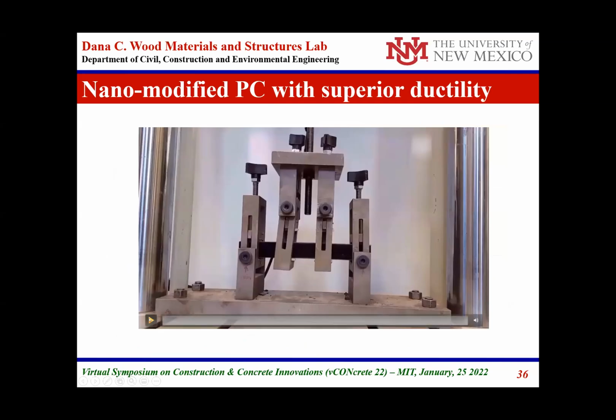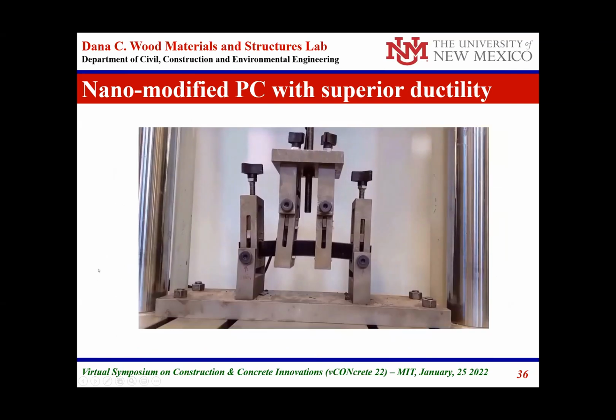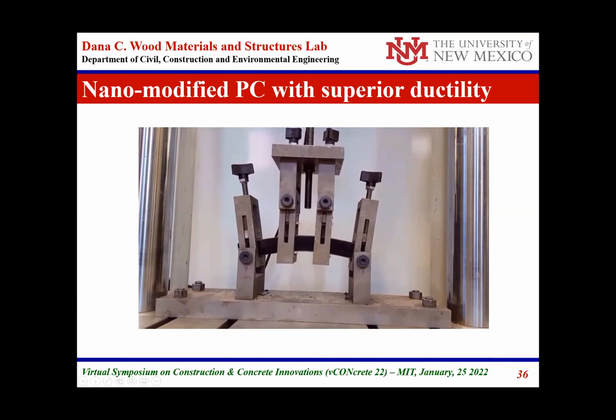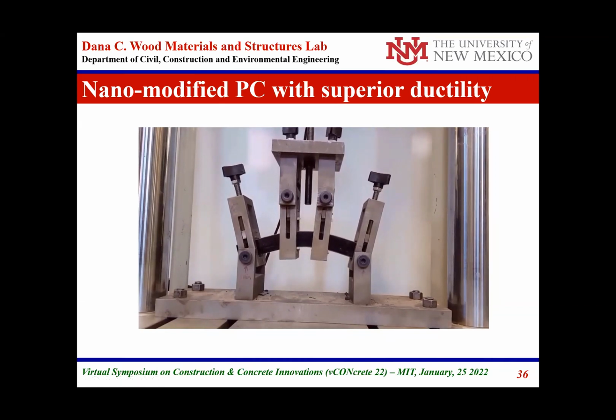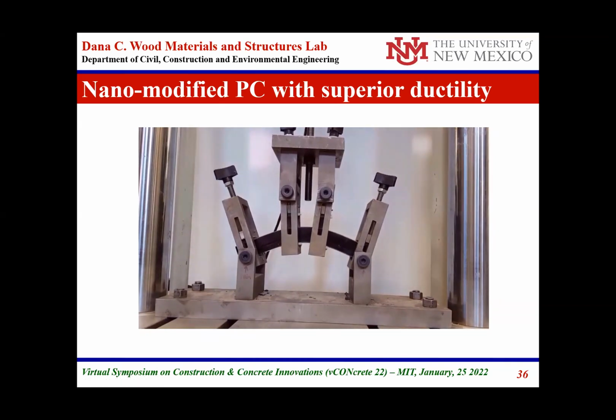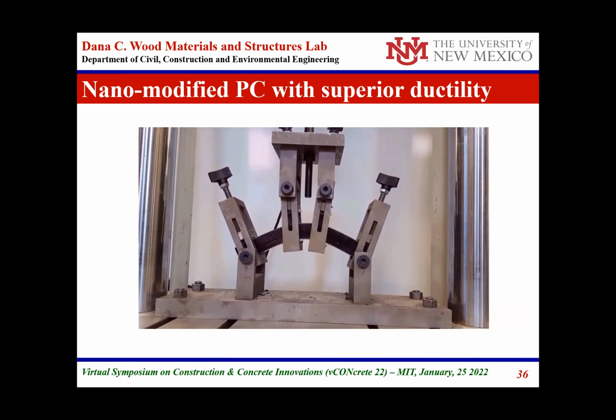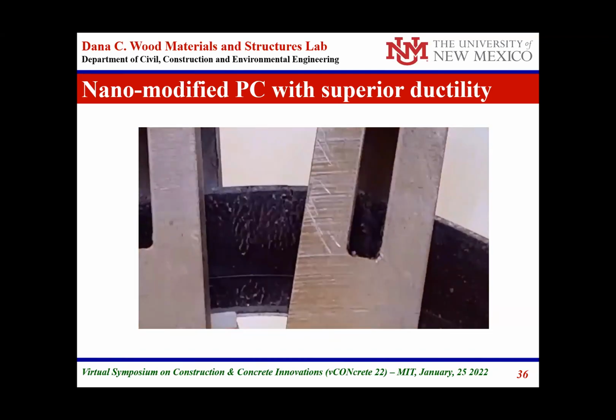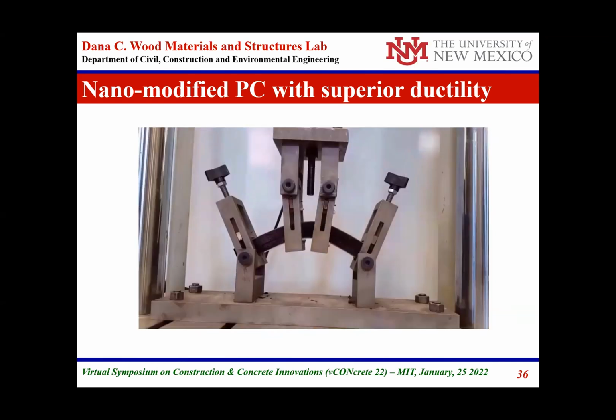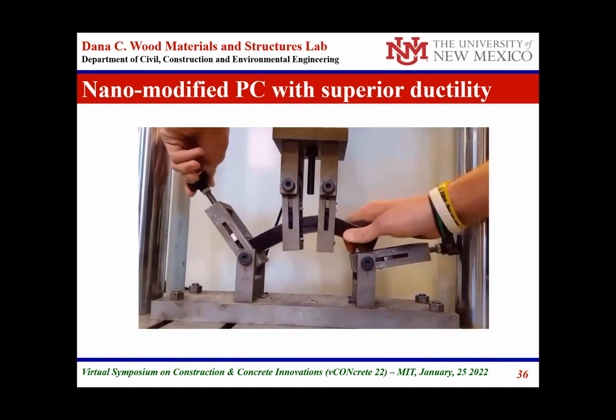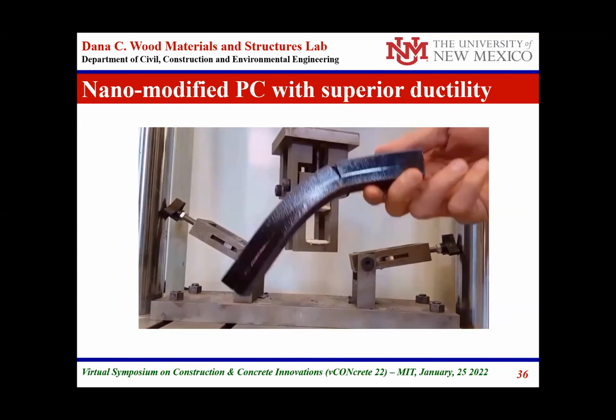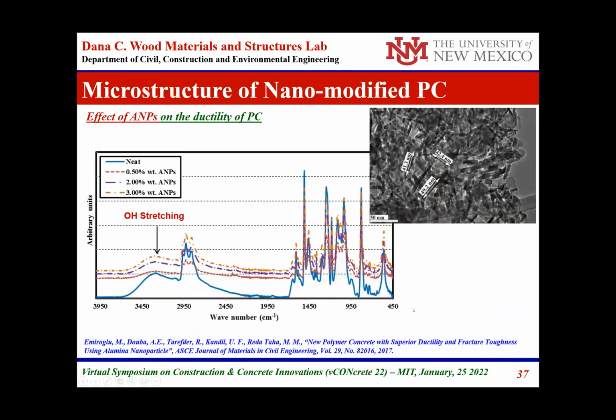This is an example of one of these polymer concretes. We can see the level of ductility of the nano-modified polymer concrete. We use this test because usually in a concrete test like this, you get complete cracking of the concrete. But here you can see that the polymer concrete bended, and actually the support failed before we were able to fail the concrete.